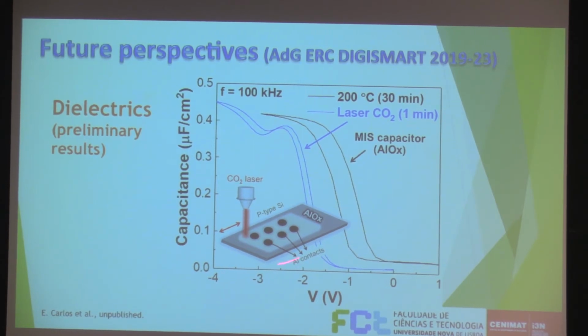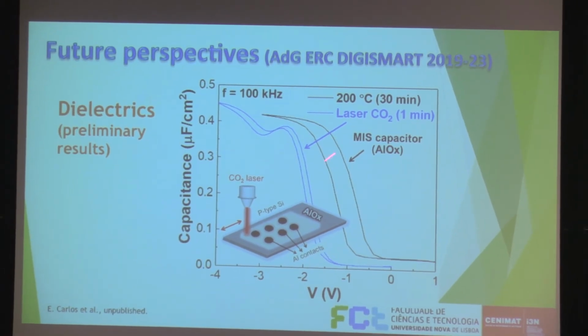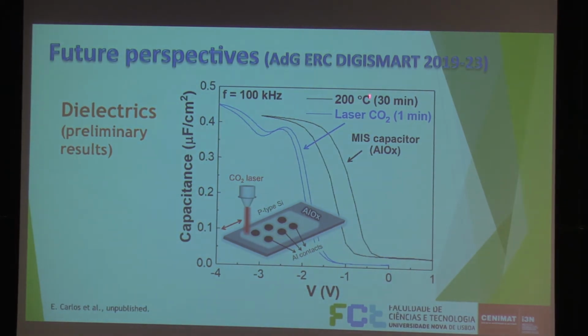For example, this is the case for a capacitor based on aluminum oxide, and we have the comparison: the black curve using the conventional process at 200 degrees for 30 minutes, and the blue one, which is also not yet optimized, using a CO2 laser for 1 minute.